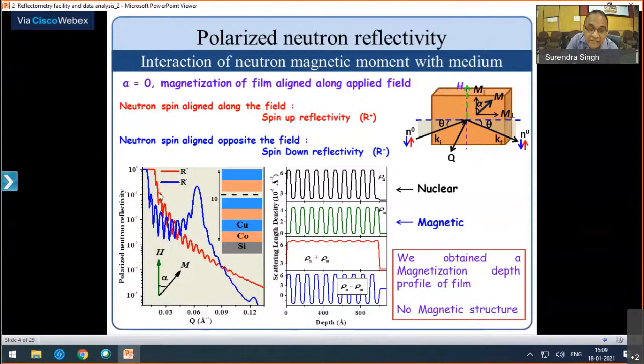That's why you're noticing in that graph - it's something like a high intensity Bragg peak. Whereas for R minus, rho n minus rho m, the contrast is very large - you have a nice Bragg intensity as well as Kiessig oscillation for R minus. So the difference between R plus reflectivity and R minus reflectivity gives you the detailed depth magnetic moment density in the field, in the multilayer.